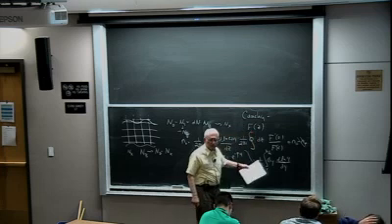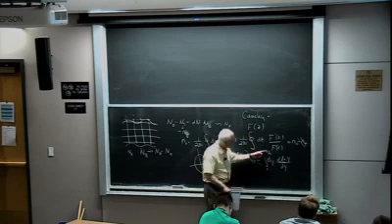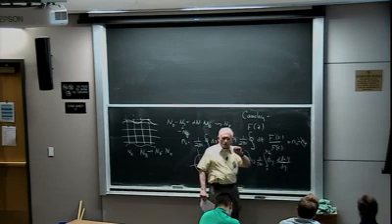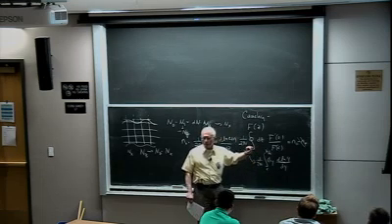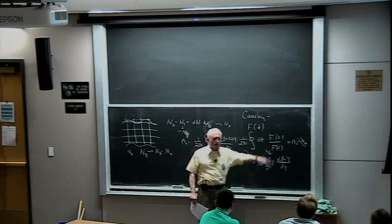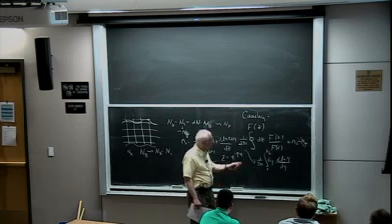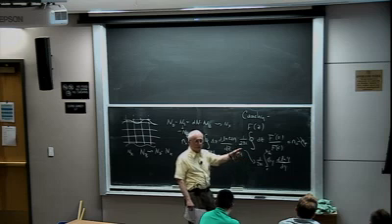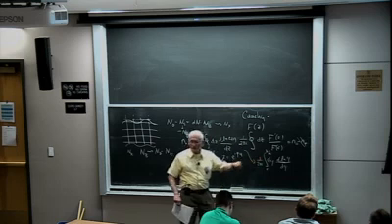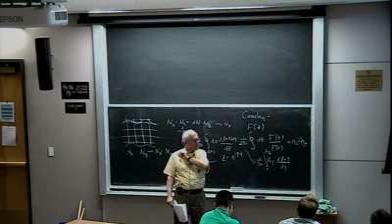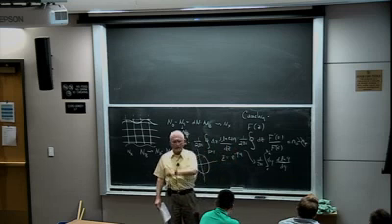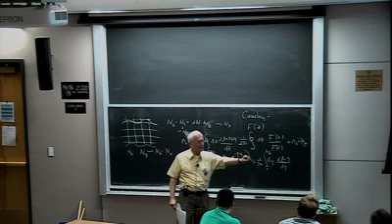And that's the same thing. And when I integrate from 0 to 2 pi, I'm going between two equivalent points in the Brillouin zone, which means that in essence, I'm doing an integral around the circle. Okay, so this gives us the 0 mode. We know from our count that we have to have one 0 mode. So we either have the case where the 0 mode is all the way across the sample, on the right side, or the left side.